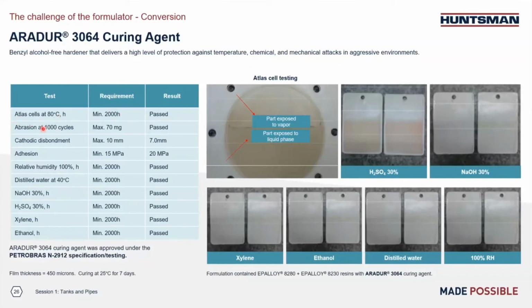You also have very good Taber abrasion results, and the weight loss is less than 70 milligrams. Good cathodic disbondment testing results, very good adhesion, and also pretty good chemical resistance like caustic, acid, and solvent. You can see the panel listing here, and other than the discoloration, the panels all look pretty good, right? So you always want to choose this kind of high performance curing agent for your end applications. And by the way, this system is based on the Novolac blends, which is EPALLOY 8280 and EPALLOY 8230, and it is cured at room temperature for 7 days before all those tests.